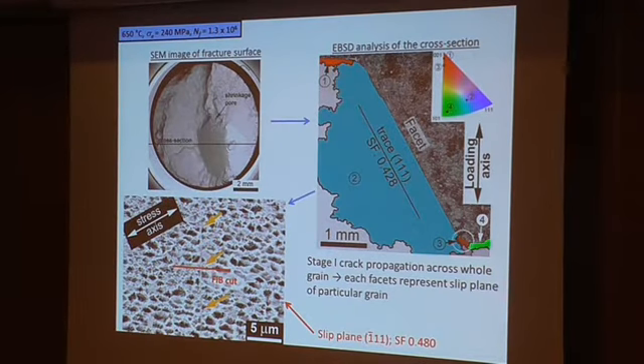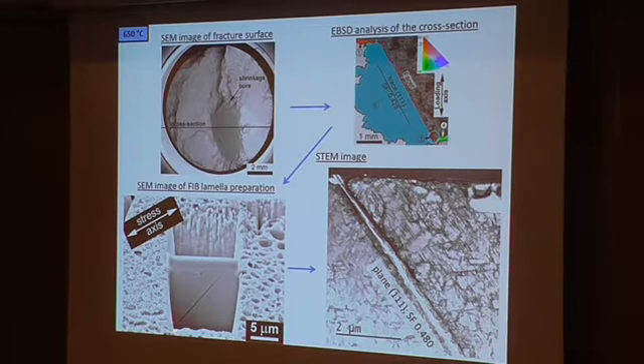And we prepared a lift-out cut by focused ion beam and scanning electron microscopy. And in another slide, you will see that in this area, it wasn't just some shearing of precipitates, but we were lucky and found an already developed stage 1 crack. And here is an image from scanning mode of transmission electron microscopy, where the crack is visible, going along the plane 111, and this plane has a very high Schmid factor. Here you can also see the planar character of the dislocation structure.